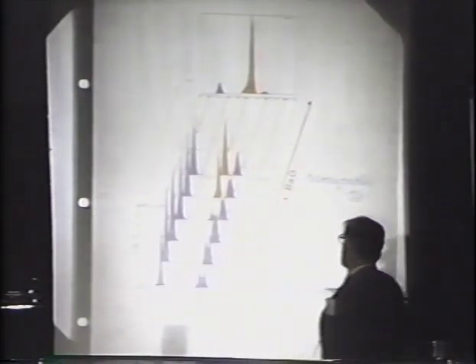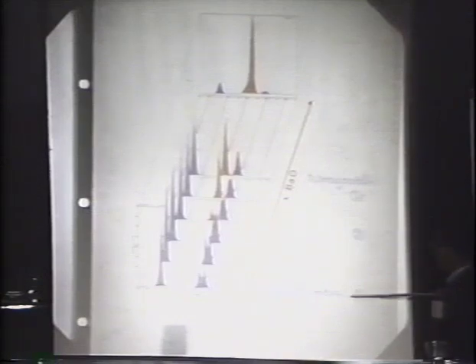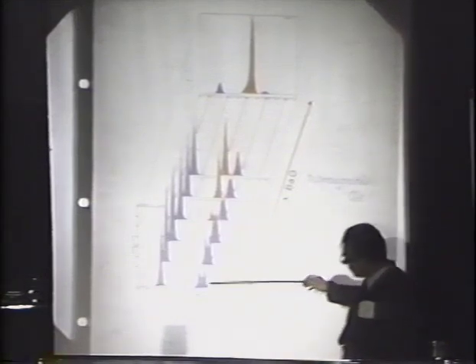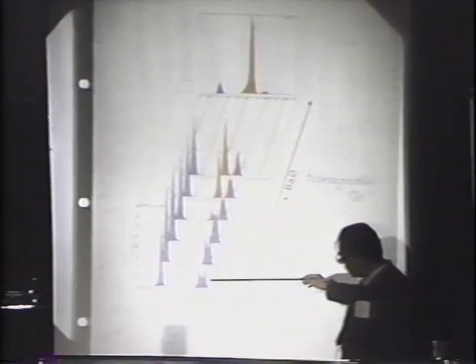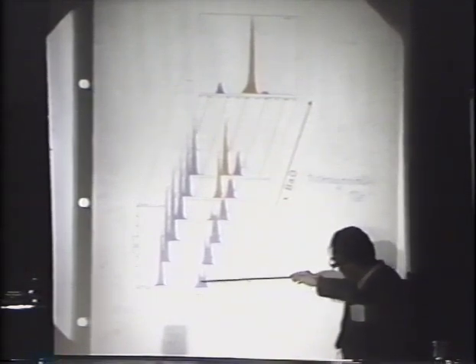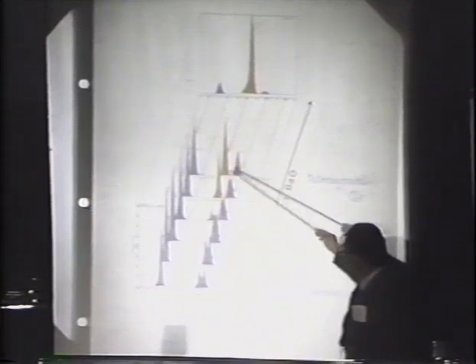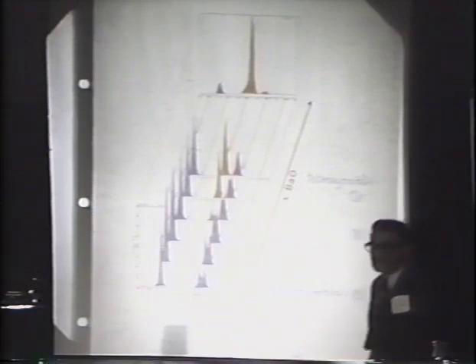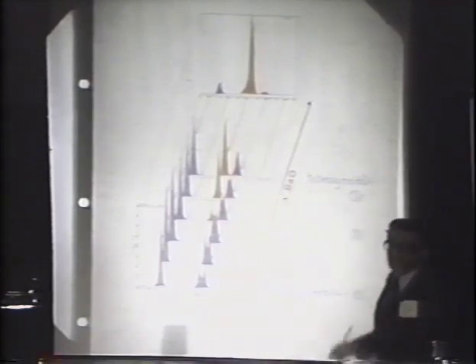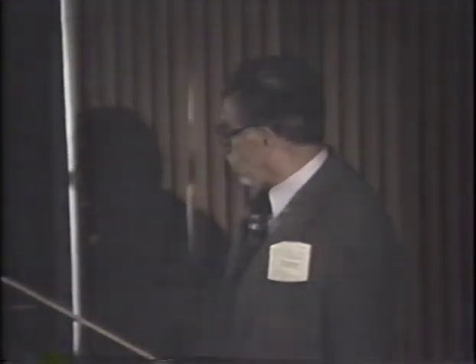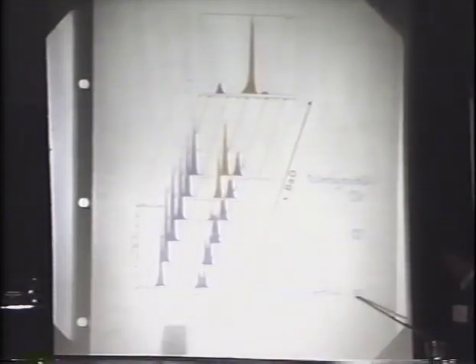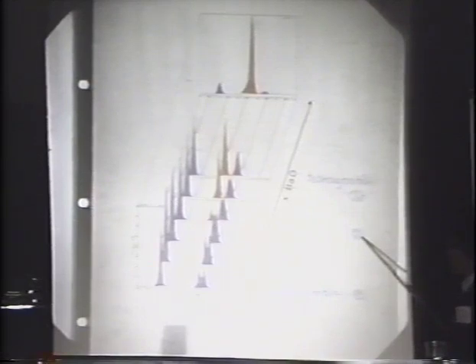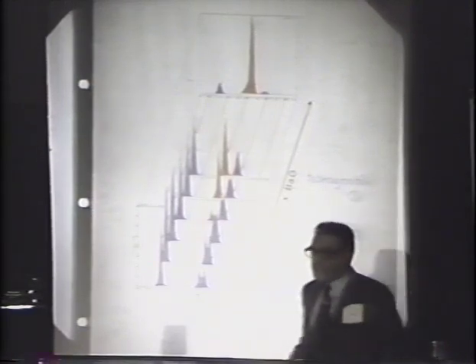So without substitution, it's orthorhombic, and when you substitute, it gets tetragonal, as exemplified here by this X-ray data as a function of the barium content. So it's split here, and smoothly you see only one line. Here it's tetragonal, and it's around this concentration where you have the optimum transition temperature observed in these layer compounds. And I showed you our data for the orthorhombic case, in between number 2 and 3, for optimum transition temperature in these layer compounds.